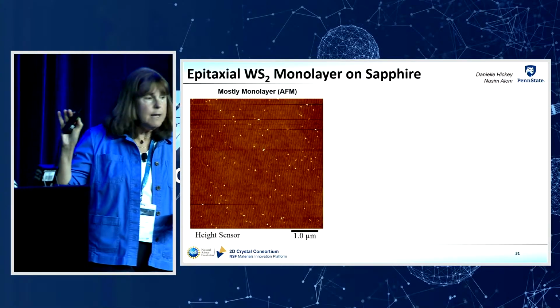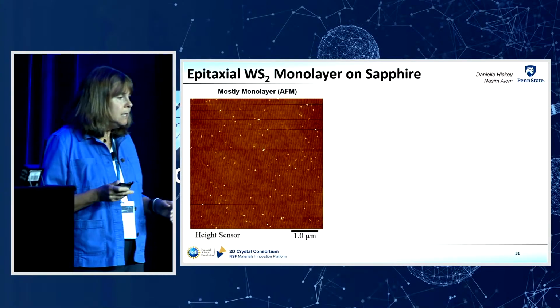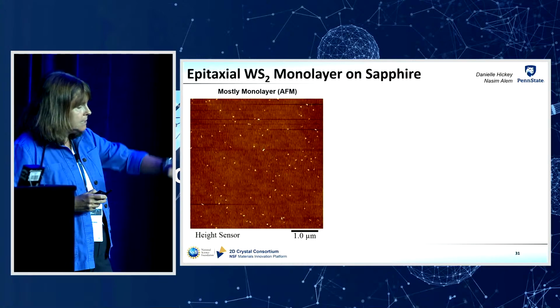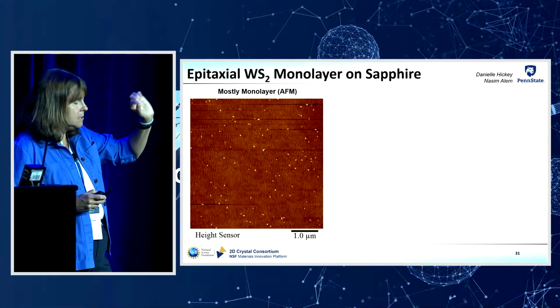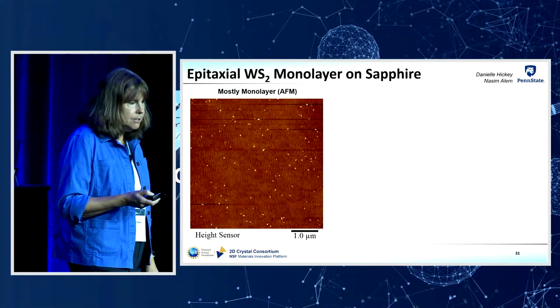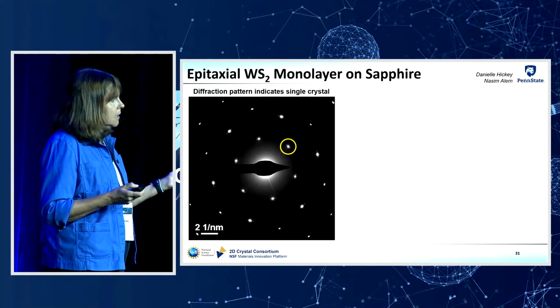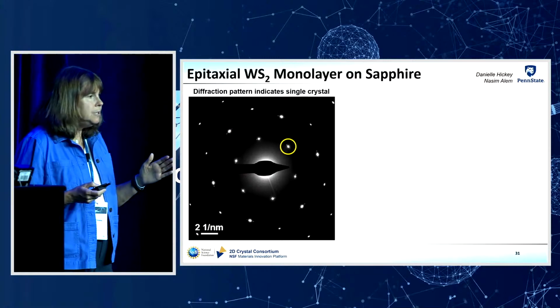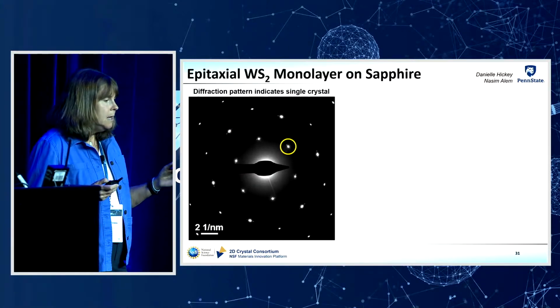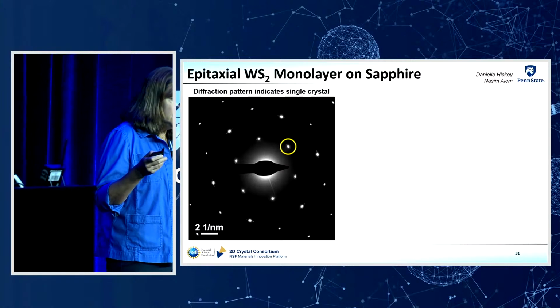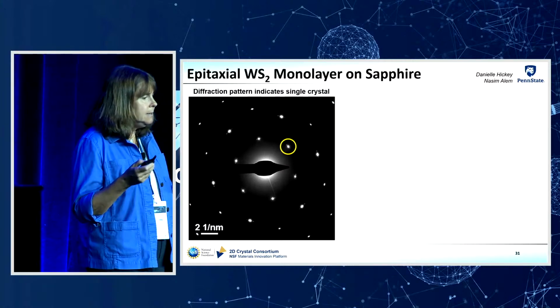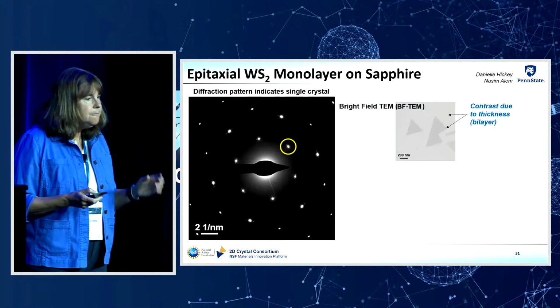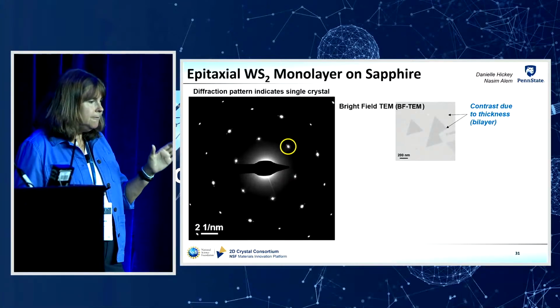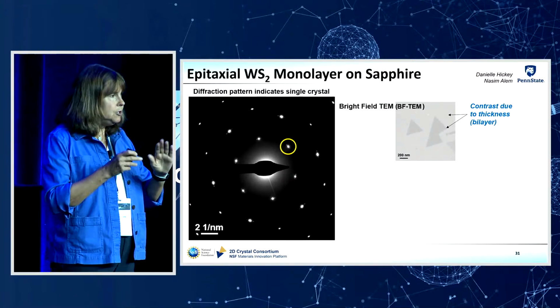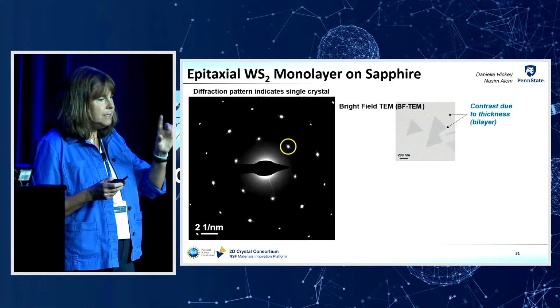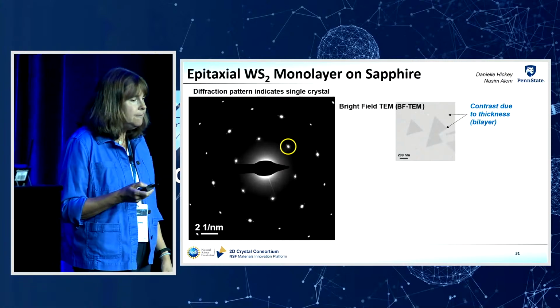And this is what the AFM looks like for this particular sample. We have a completely coalesced monolayer, and then these little white specks, those are bilayer domains that have started to nucleate. So if we just look at this film using electron diffraction, we see a spot pattern, right? So that indicates that the film is single crystal. If we look at this film using bright field imaging, we see contrast that's just due to bilayers. So you can see clearly the bilayers in a bright field image.